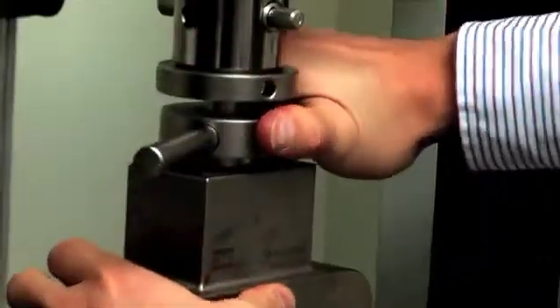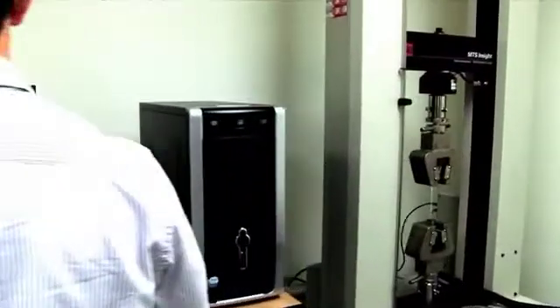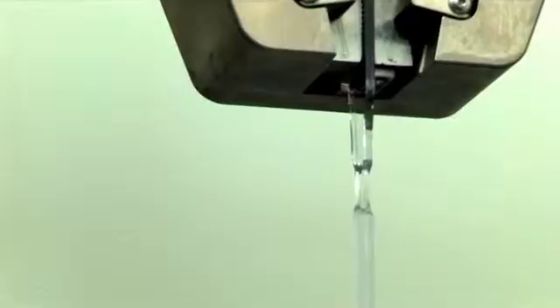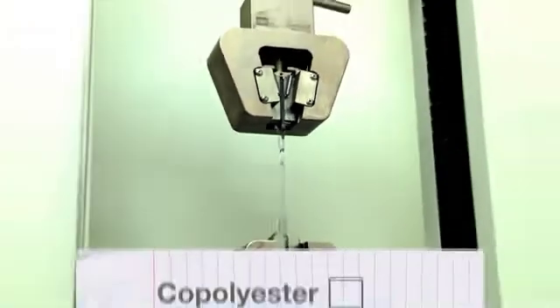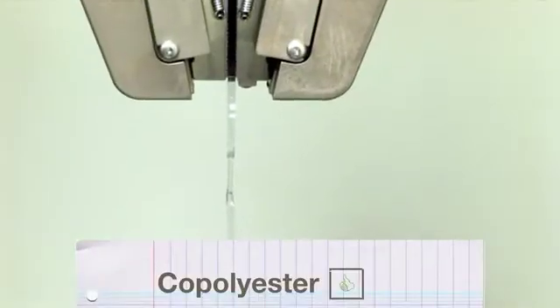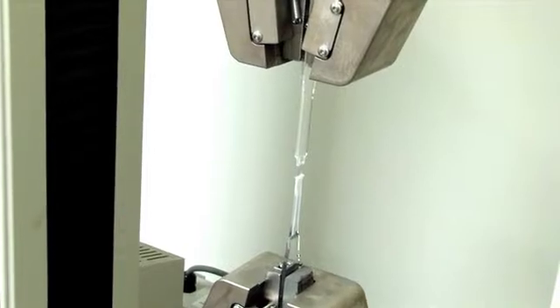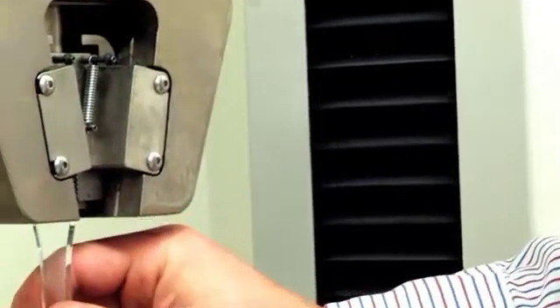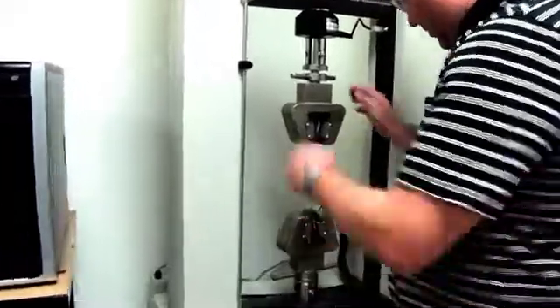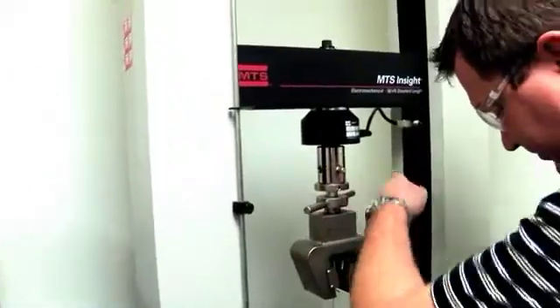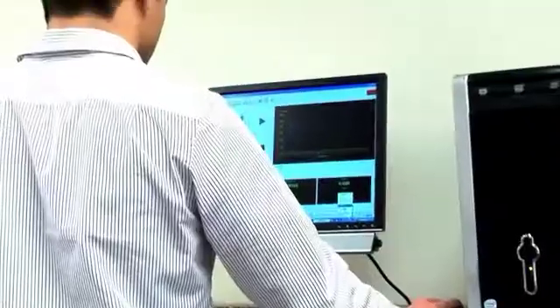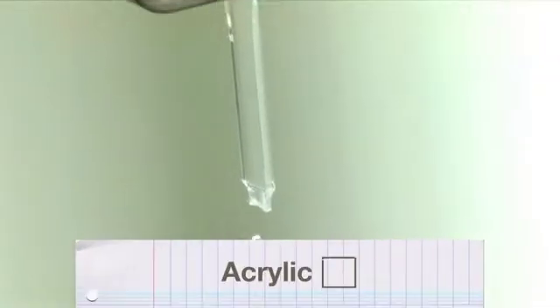In a first example, we'll show you how copolyester performs in a typical tensile test. As you can see, the material pulls and stretches and elongates, but it doesn't break until it gets to a critical point. As a comparison, here's an example of how acrylic performs in the same test. The material does not elongate and actually results in brittle failure fairly quickly once it yields.